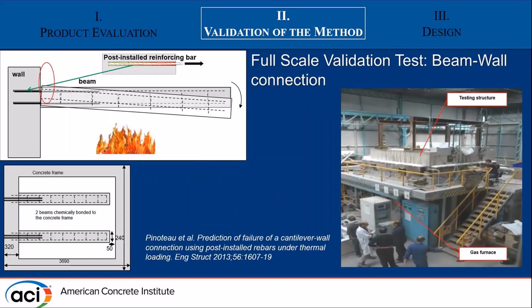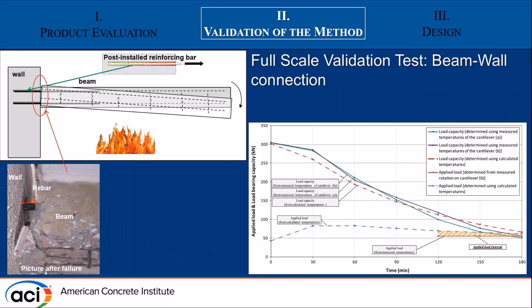So we did two full-scale tests. The first one was on a structure which was a wall cantilever beam, which was connected to a wall using post-install rebar. Here, the bonded part of the rebar is only inside the wall, not inside the beam. There were two beams in order to check repeatability. We took the tested structure and put it on top of a furnace where we applied an isofire up until collapse. And we measured the collapse.